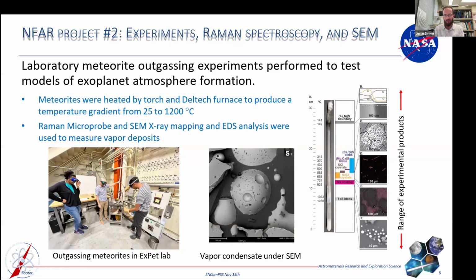So you can see in the middle, you have some condensates from those vaporization and condensation experiments under the SEM. Those are little particles. But what was really clever about this, and enabled by our team, was that they were able to produce these experiments within basically a test tube. It's not a test tube, but it's basically a test tube. Without opening it up, they were able to use the Raman to evaluate the textures, the minerals, and the composition of those.